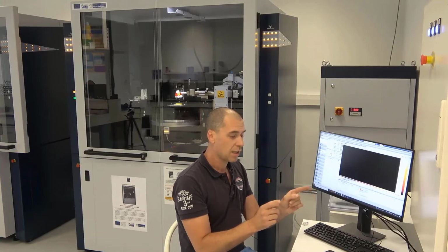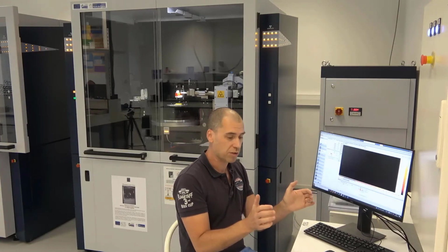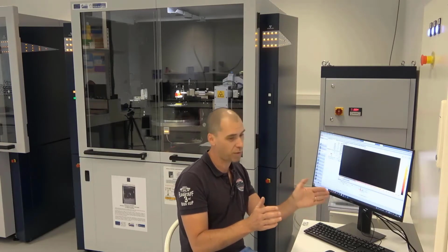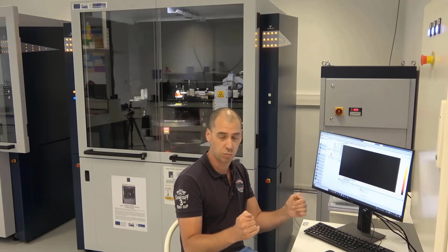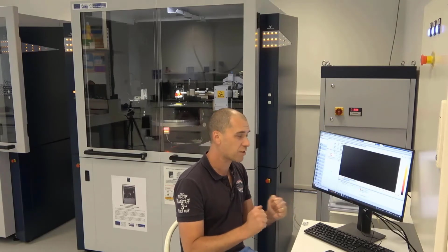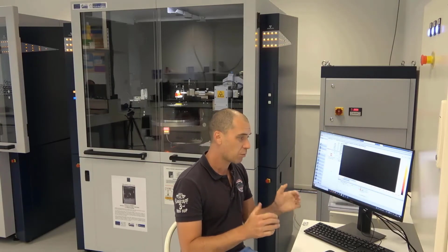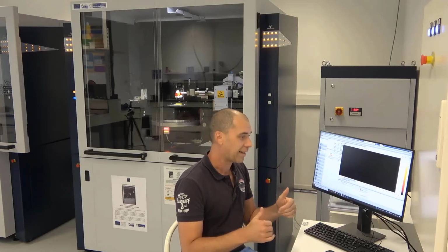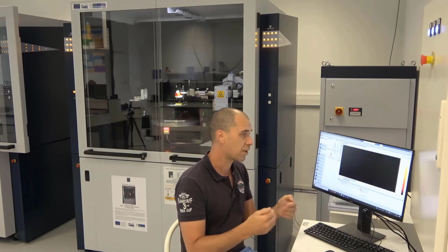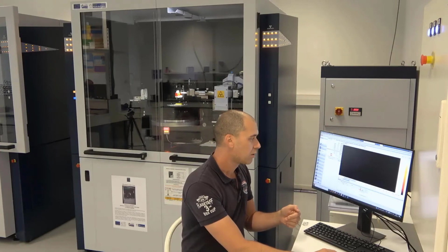So I can position the middle of my detector at about 14 degrees 2theta. And thanks to the wide aperture of the detector, I'm able to measure from about 7 degrees 2theta up to 22 degrees 2theta using the molybdenum radiation, which is quite a large Q range. So using snapshot, I can do fast measurements with high quality data. And I can repeat that during the cycling of my batteries to see in real time how the cell parameters of my materials are evolving.